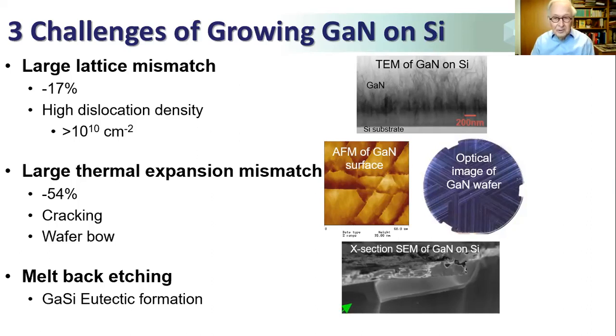And then the third problem when you grow gallium nitride on silicon is that you get a gallium silicon eutectic formed, called melt-back etching. You can't then grow devices on this. Whereas when you grow gallium nitride on sapphire, you don't get this melt-back etching. So these are three problems you have to solve if you're going to grow gallium nitride on silicon devices, and you need really basic science to solve these three problems.